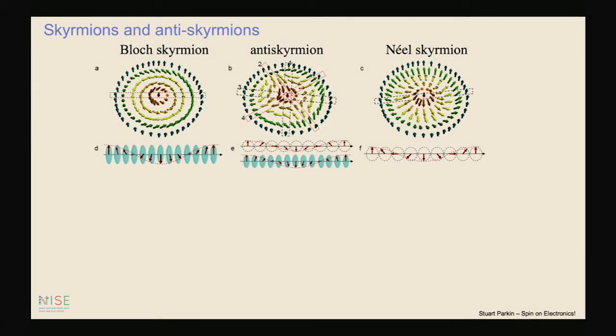Both of these objects have been discovered in a number of distinct material systems over the last 10 years, from the original observation of skyrmions in manganese silicon, which is a chiral system. Now, what we discovered 2 years ago is the middle object, an anti-skyrmion. So let me try to explain what that is. That is a system in which, as you move around the domain wall, the wall around the circumference of this circular object changes from being a Bloch wall to a Néel wall to a Bloch wall, etc.